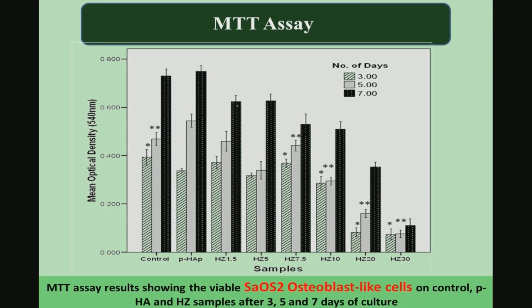A similar observation is largely valid when quantifying cell viability using osteoblast-like osteosarcoma cells. Twenty and 30 percent zinc oxide are clearly worse in supporting cell viability, while 10 percent shows statistically significant differences but may still be considered acceptable with respect to control parent hydroxyapatite. Osteoblast cells show tolerance up to 10 percent zinc oxide, but overall, hydroxyapatite with 5 percent zinc oxide is safer for cell compatibility than 10, 20, or 30 percent.